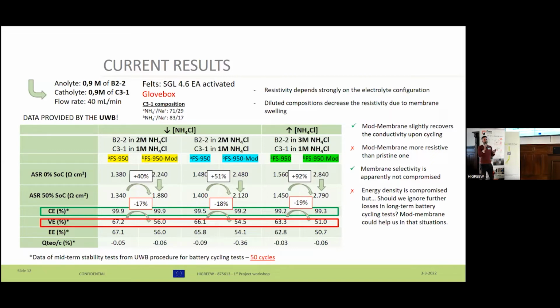But I would like to say that this data is considering 50 cycles. So let us wonder what will happen at 1,000 cycles or 1 month of operation of the battery, no? This fact lets us wonder if we should ignore further losses in long-term battery cycling tests, because maybe modified membranes could help us in that situation, because the crossover is something that we will have to face at a certain time. So it needs to be analyzed in long-term experiments, and very important, even if we want to compare the different membranes with a very well-defined electrolyte configuration. If you have different situations, the comparison is much more difficult.